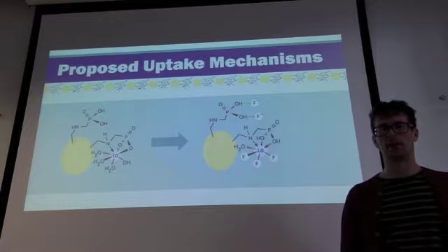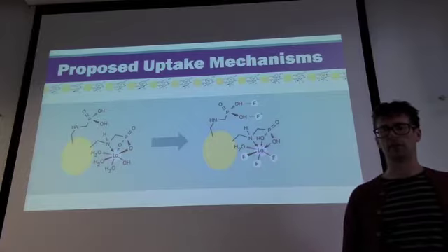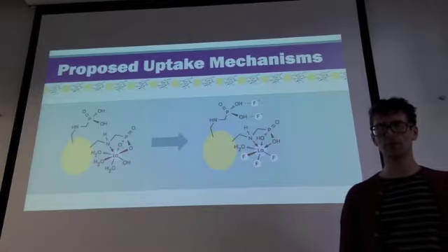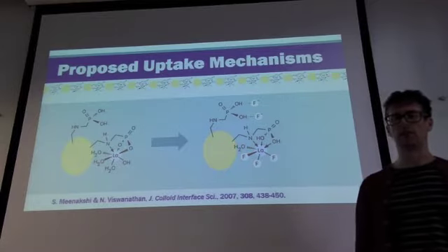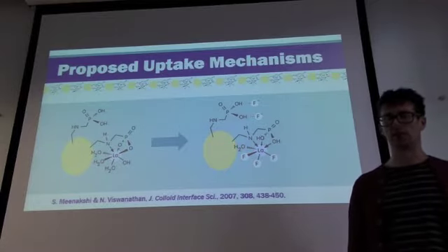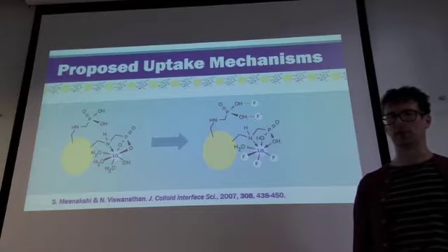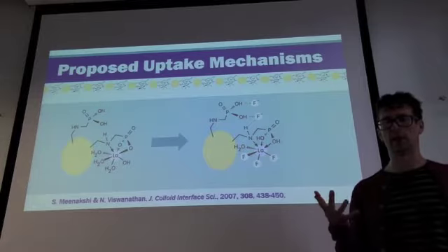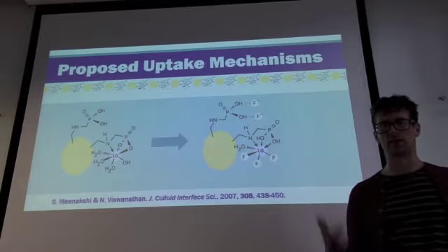But it actually turns out that at peak capacity, the ratio of fluoride to lanthanum is far, far in excess of what can be explained by this. So it means the secondary H-bonding process must also be occurring. And indeed there are examples in the literature that shows us that such interactions do readily occur. So those 2 processes explain the initial shape of the kinetic graph.